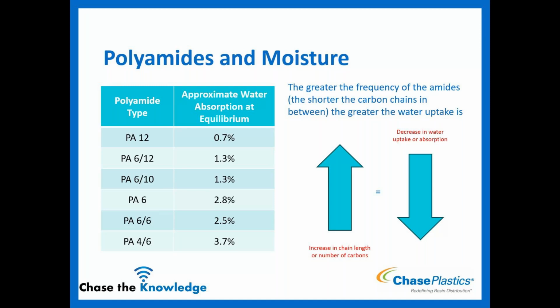And so what does that look like from a value perspective? We have the different nylons listed out. These are the common ones that I'm going to talk about throughout my presentation. But if you look at 12 carbons on the backbone, a longer chain nylon, you're looking at 0.7 for absorption at equilibrium. Now, if I jump to something like a 6 or a 6,6, where there's 6 carbons instead of 12, so half as many, it jumps to 2.8 or 2.5. And then even further still, if I lose just 2 carbons on the backbone between a 6,6 and a 4,6, I jump up to 3.7% at equilibrium. So longer chain ends up being lower moisture absorption. Shorter chain, more moisture absorption.